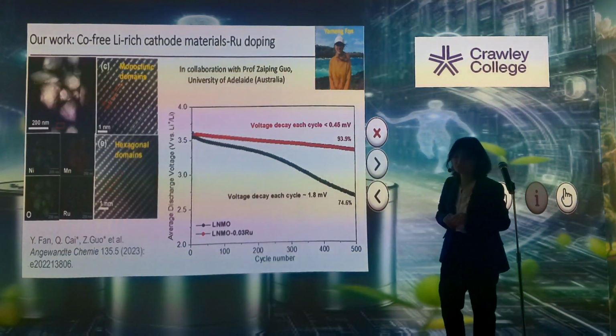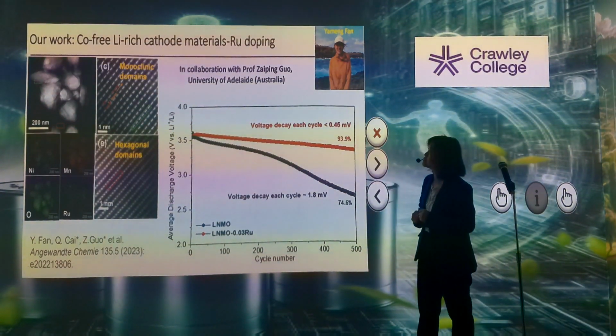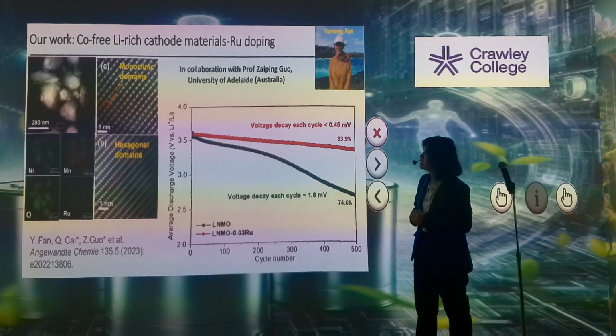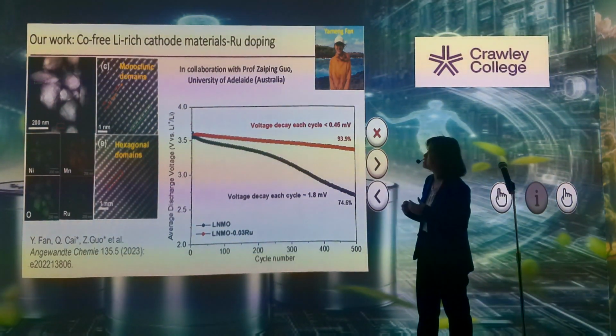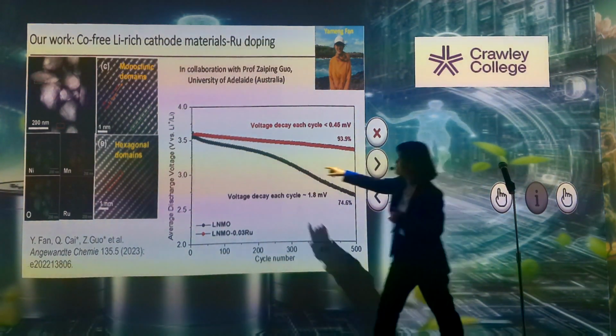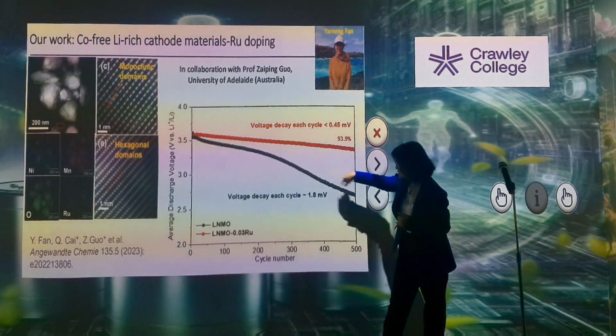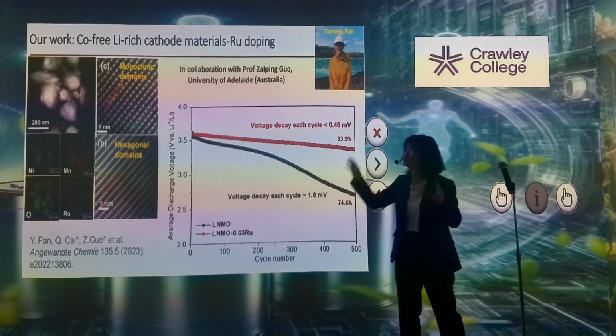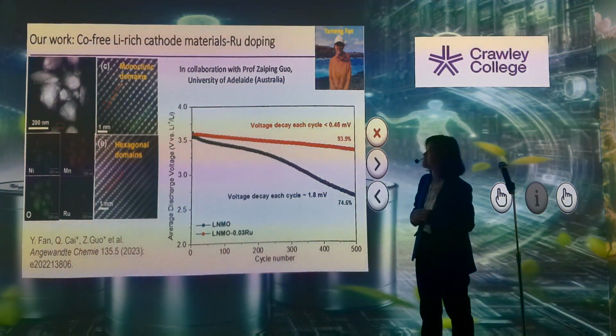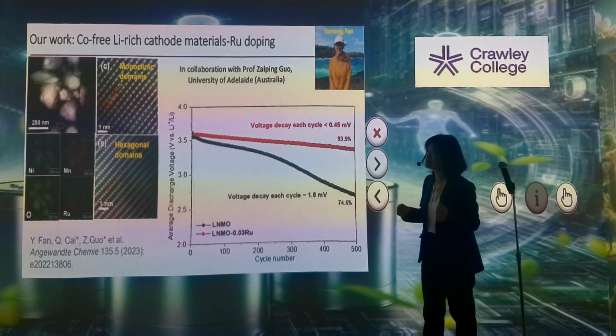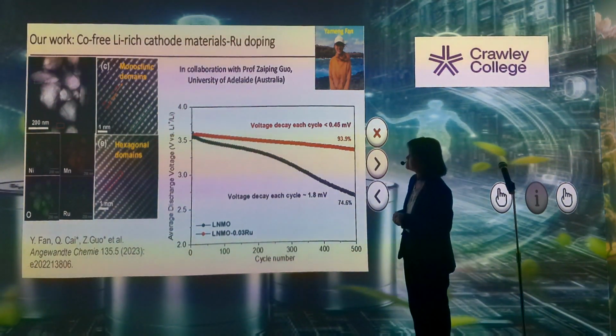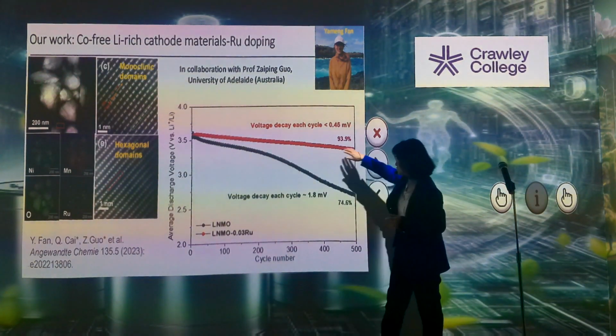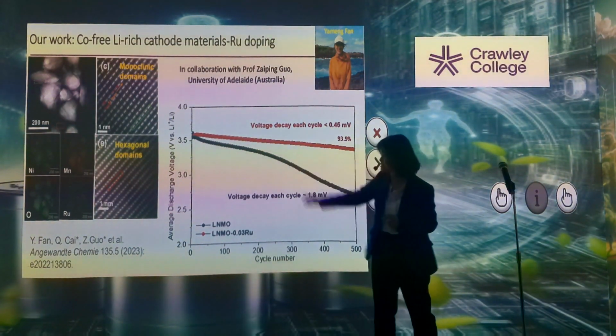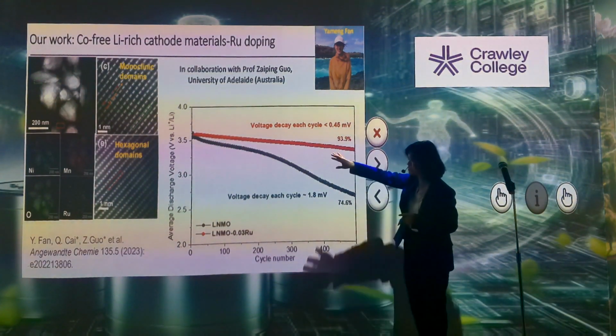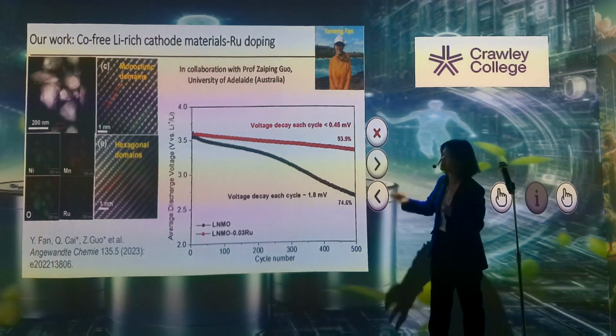However, there are some challenges with those new materials. So my PhD student Qiong tried to improve the performance of this lithium-rich, cobalt-free cathode material. They typically have a very bad voltage decay, as you can see in the black line. So what she did was try to dope ruthenium into this material, only 0.03% weight, and it significantly improved the voltage stability. I like the fancy high resolution TEM images there showing that the material is what we have produced.